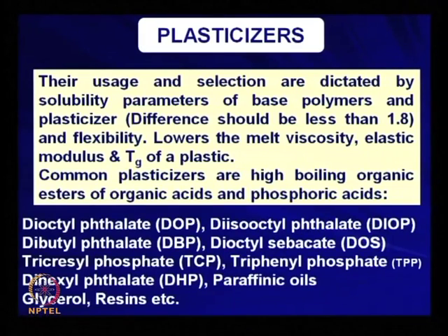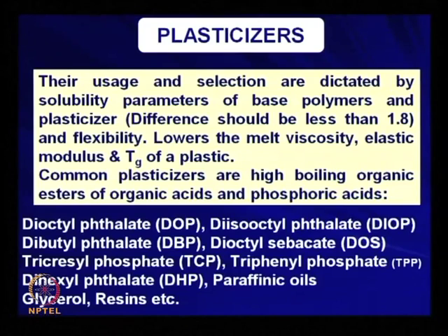Plasticizers, this is the most important thing. I told you what plasticizers are. These are low molecular weight organic esters, and provided the solubility parameter of the plasticizer is very close to that of the polymer, only then can a particular ester compound be useful as a plasticizer for one particular polymer. So there are a large number of examples, say dioctyl phthalate, dibutyl phthalate, tricresyl phosphate, dihexyl phthalate, triphenyl phosphate, dioctyl sebacate, etcetera, glycerol, resins.